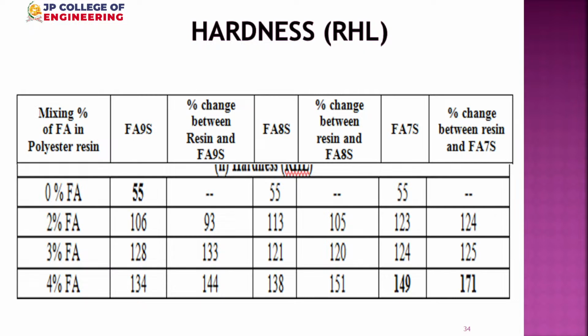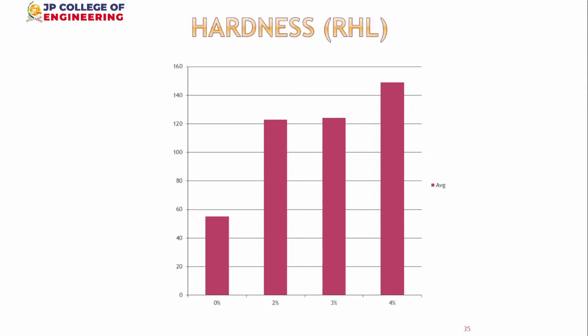So which gives a high hardness value. Whereas where the percentage is low, it is adequate. But if hardness alone is the criterion, then one can say you can go for the 4% one. But strength-wise it comes down. That point should be noted. Next slide, please. Yeah, so on this hardness comparison, you see 2% and 3% are almost comparable, but 4% is somewhat high. However, strength-wise, the third is a better one. Next slide, please.